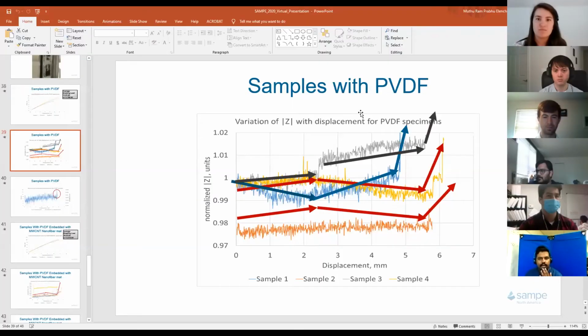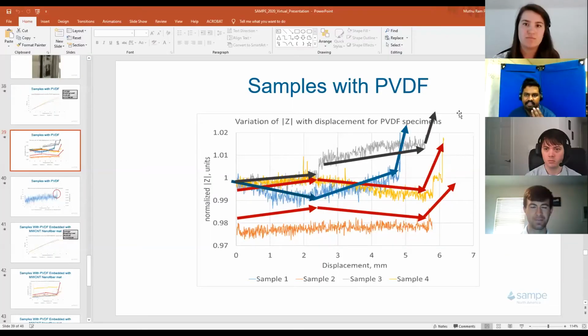Okay, thank you. Muthu, what is your interpretation of the random behavior of the PVDF samples in the impedance versus displacement graph? So this is the PVDF samples data, the impedance versus displacement graph. For two samples, we observed a steady increase, decrease, and again an increase. But for the other two samples, it was a different behavior.